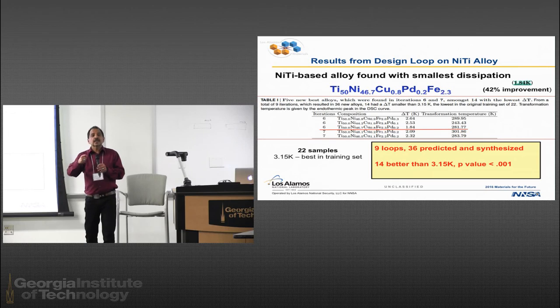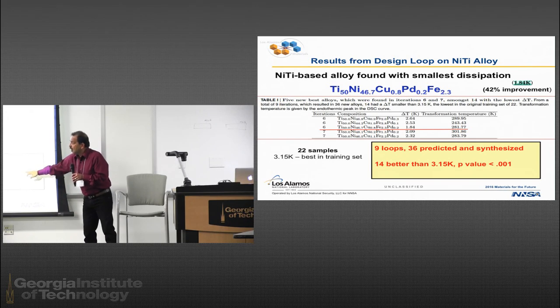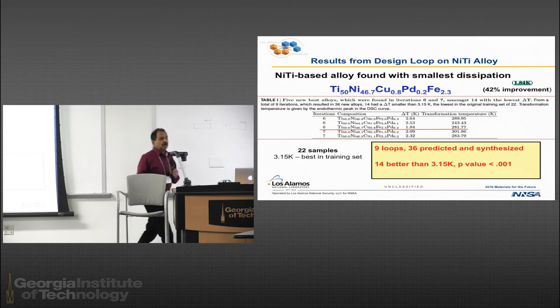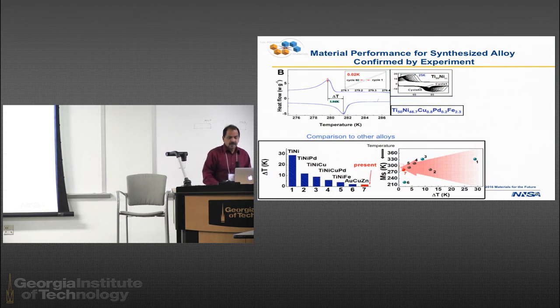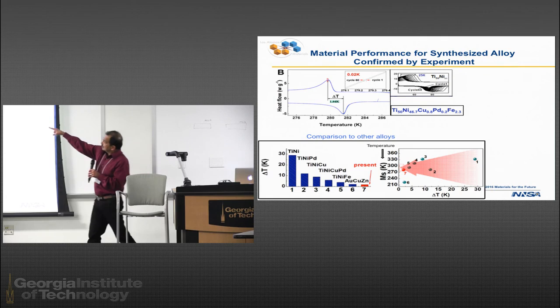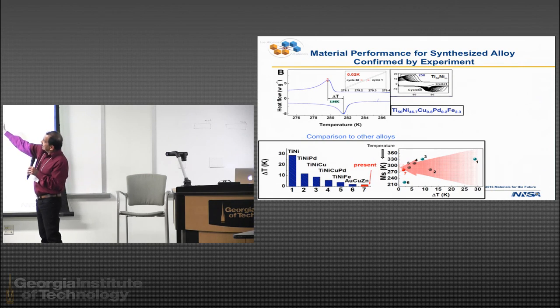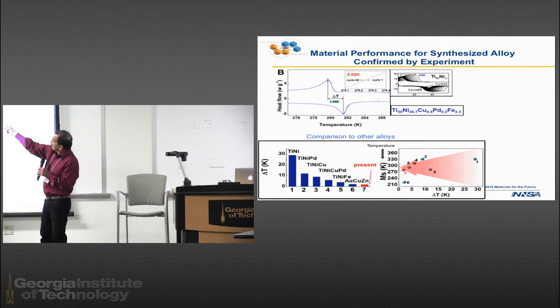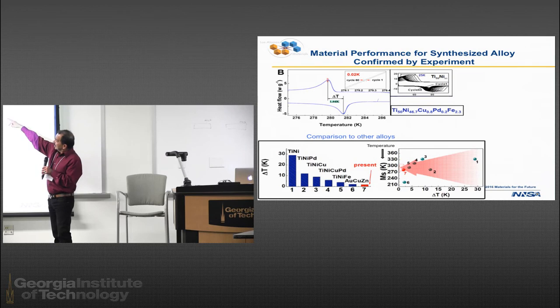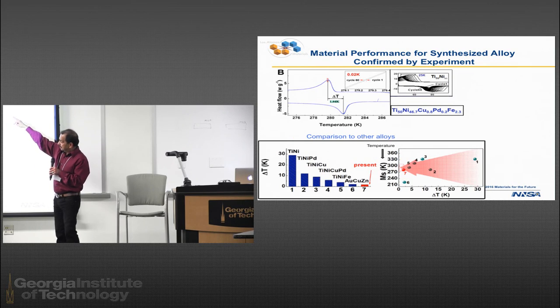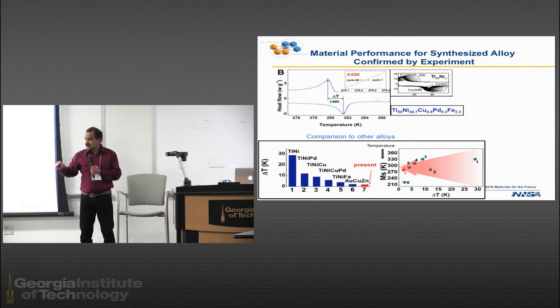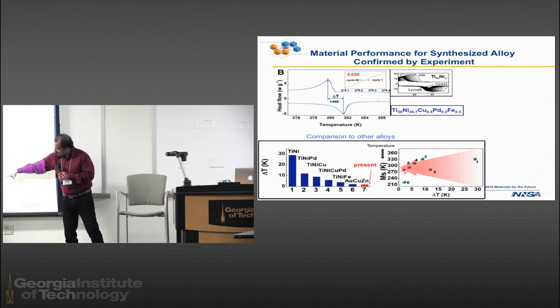14 of them were better than the best in our training set. And so the p-value is very small. There's no way that we could have found this compound on a random basis. If you want to know how good it is, this shows you that the shift in the temperature, delta T, over 60 cycles is very, very small compared to something like nickel titanium. And one of the things to point out is that our compound is very competitive in the landscape of compounds.